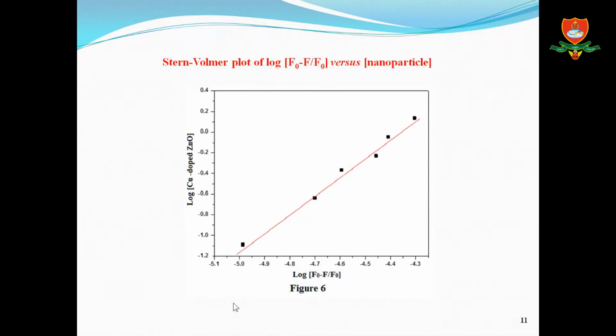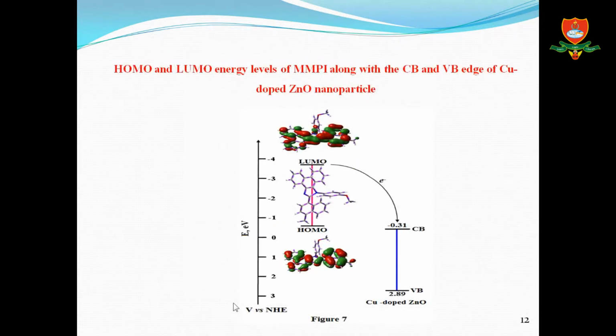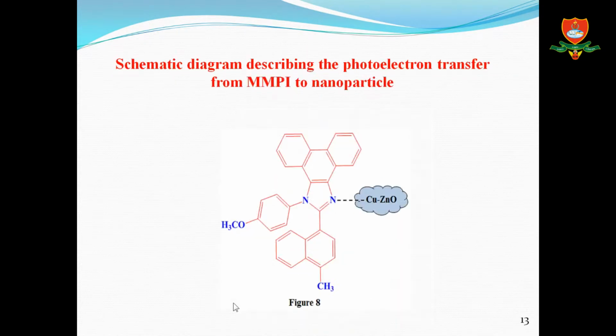The good linear relationship between 1/F0 and the reciprocal concentrations of nanoparticle. The relative HOMO-LUMO energy level of an isolated MMPI molecule, along with the conduction band and valence band edges of copper-doped zinc oxide nanoparticles. Its expanded quenching process conforms to binding of MMPI with copper-doped zinc oxide.